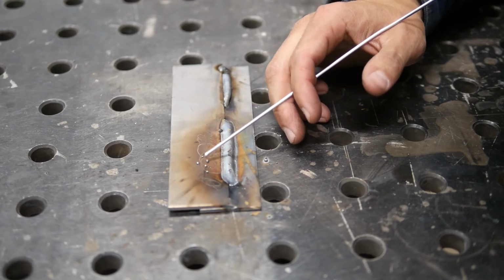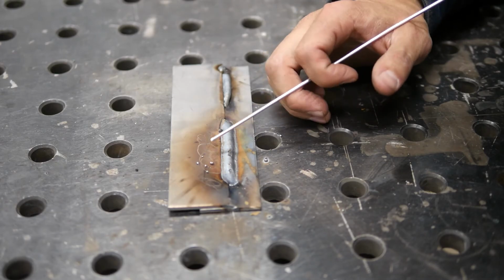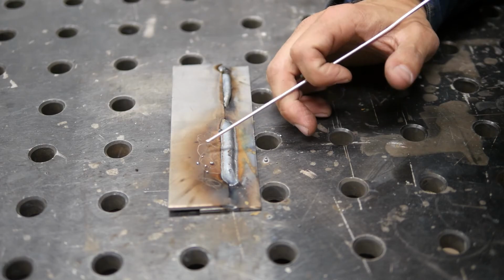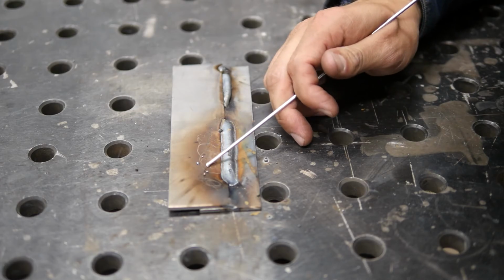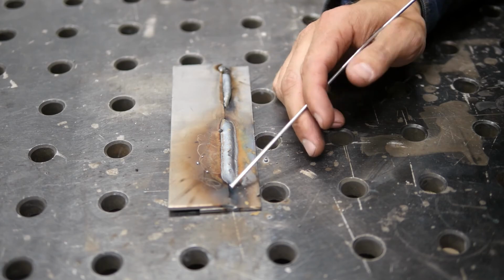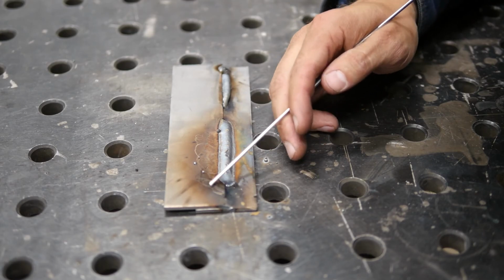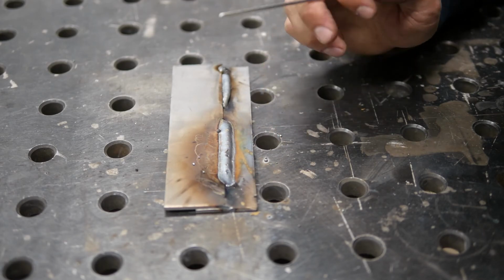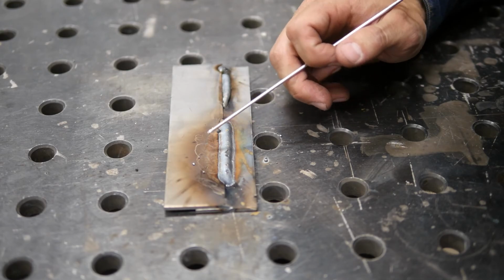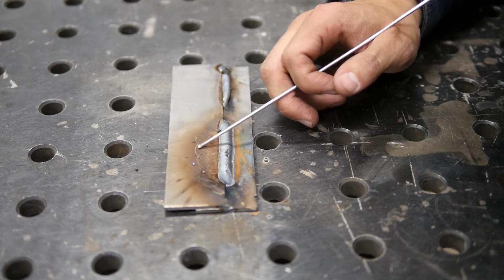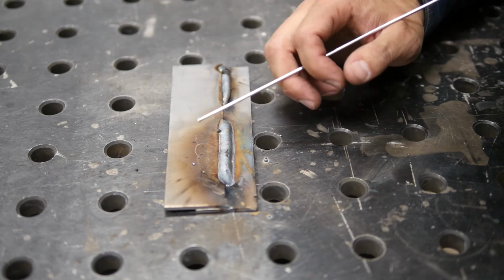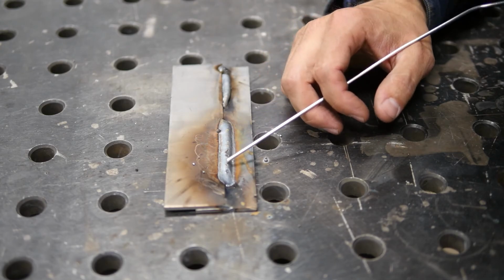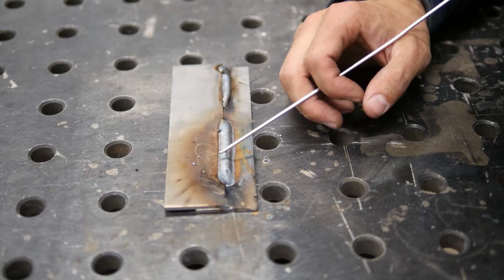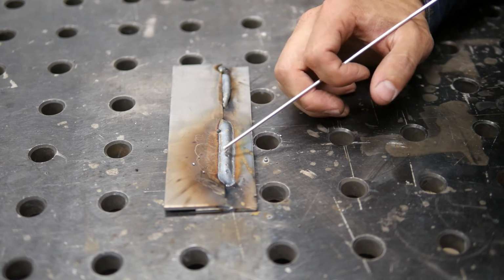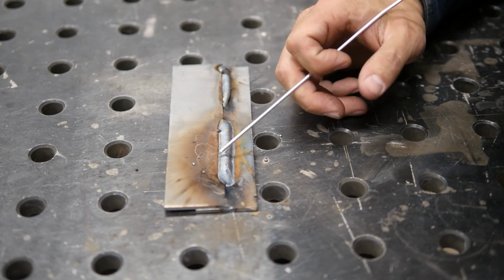Now, this is not the biggest deal in the world. It's just more cleanup you have to do in the end. But the thing that I don't really like is all of the soot on the weld. You can see this soot here, and what that is caused by is this spatter flying through the arc and creating turbulence, and then it starts to suck in atmosphere, namely nitrogen. And I know that when nitrogen gets into our liquid metal, we get iron nitride, which can make the weld brittle, and of course we don't really want that.